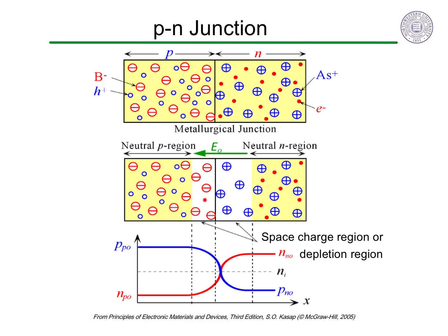The uncompensated charges produce an internal electric field from positive to negative. The electric field would push holes back towards the p-type region and electrons back to the n-type region. This built-in electric field then opposes further diffusion of both electrons and holes. In this way, the electric field will build up until an equilibrium is reached where the drift and diffusion forces balance.